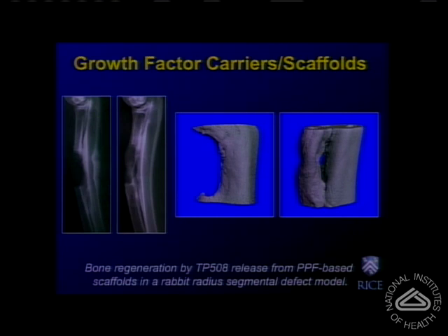We expected that the release kinetics would be very important and that a sustained release would result in more bone formation compared to immediate release, but we found the opposite result. And in retrospect, when we examined the role of these bioactive molecules in tissue regeneration, we realized that this molecule is a chemoattractant for inflammatory cells, so it's very important to release the molecule immediately to recruit the inflammatory cells to the vicinity of the defect, and it is the inflammatory cells that will secrete the mediators of bone formation and regeneration.